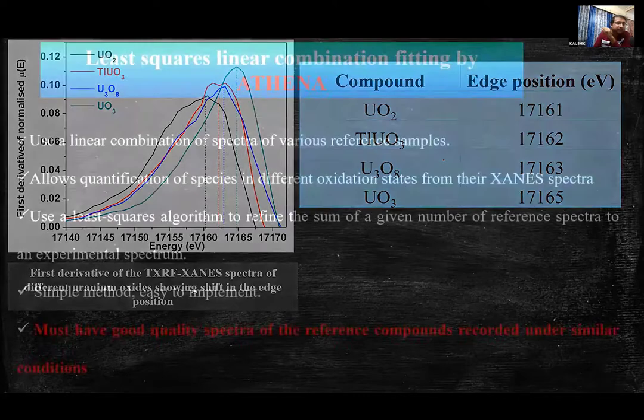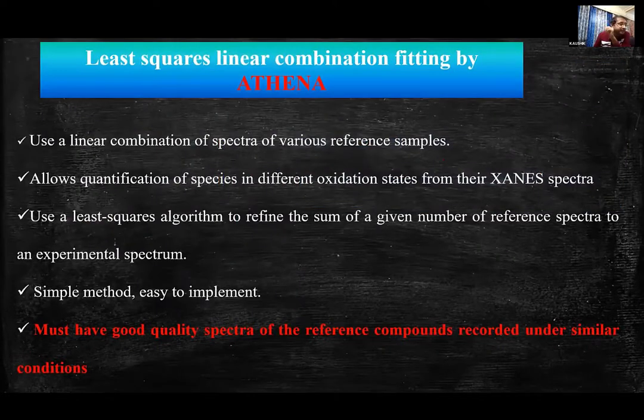But to get confirmation, we have to do the linear least square fitting process, which has been done using software called Athena. In Athena, we take the TXRF-XANES spectra of various reference samples, that is uranium oxide, titanium uranate, and UO3.